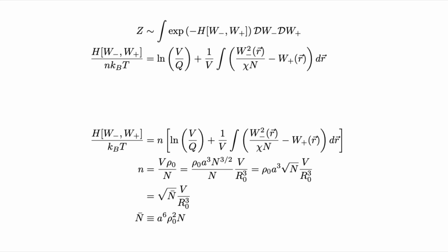This quantity n bar, called the invariant polymerization index, sets the strength of fluctuations. Unlike capital N, which is arbitrary, you can chop up the polymer into however many pieces you want, n bar is not arbitrary. A given polymer has a specific n bar. Physically, n bar tells us the degree to which polymers overlap. Larger n bar means each polymer is sampling more of the system, meaning that the environment that the polymer experiences is closer to the average environment, i.e., fluctuations far from the average are less likely.